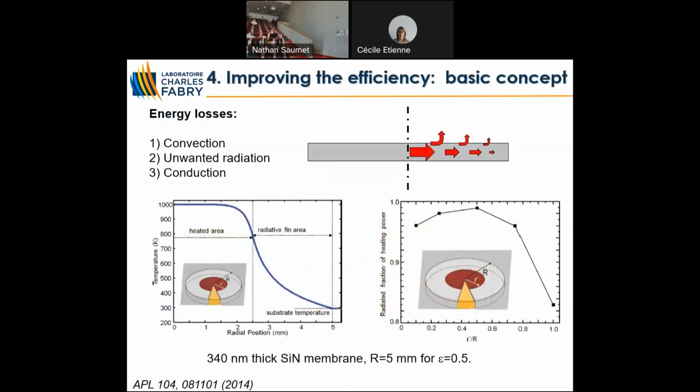How do we solve the issue of efficiency? Is it possible to have an incandescent source, a light bulb, which is efficient? In the visible, no. In the visible, you all know that the light bulbs are operated at 3000 kelvins to emit in the visible. At 3000 kelvins, you vaporize the metal. So you need to have gas to collect the vaporized metal and redeposit it. So it's a very complex chemical process to increase the lifetime of the light bulbs.